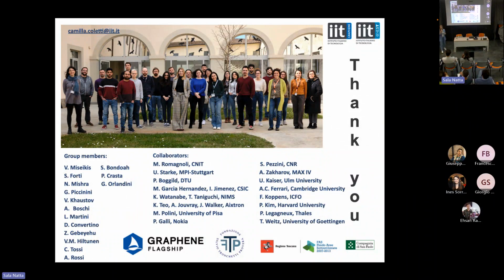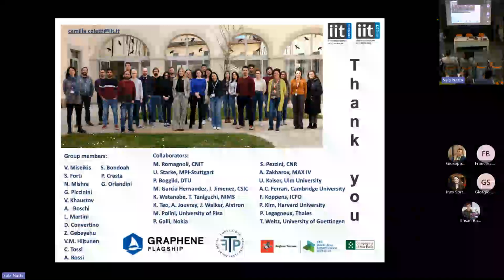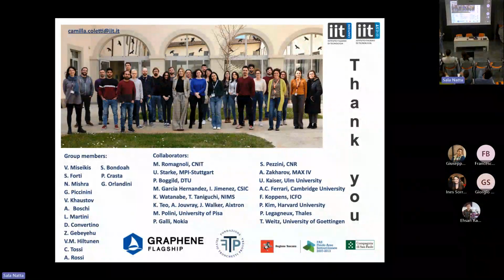And in that case, the mobility is not very good because the starting material is difficult to grow. Insulators are usually more difficult substrates to grow high quality graphene. So the best mobility we usually approach is around 5,000, but on silicon carbide. Silicon carbide is a great substrate for growing graphene because it's oriented, it has carbon inside, so you don't need to flow any methane.